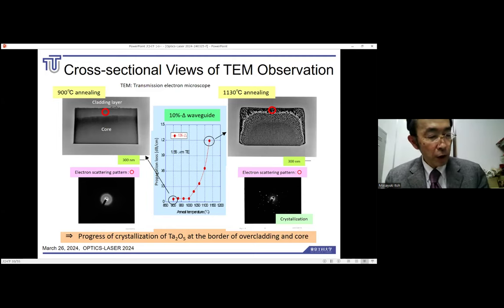Next, we used transmission electron microscopy, TEM, to observe the core cross-section of a 10% delta waveguide at different heat treatment temperatures. The horizontal axis shows the heat treatment temperature, and the vertical axis shows the propagation loss. As you can see, there is no particular problem with the cross-section in the 900 degrees Celsius heat-treated waveguide, which has very low propagation loss. However, in the 1,130 degrees Celsius heat-treated waveguide, a particle-like material was observed inside.